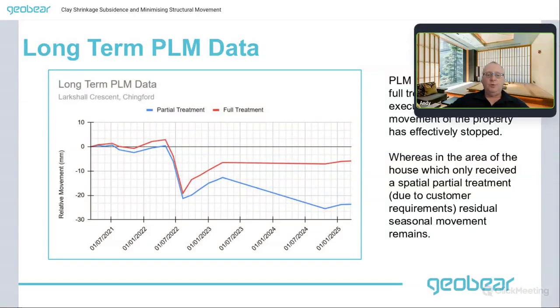Now, you may be wondering what's happening over here, where we have a downward movement and then a rebound, and then a leveling off of movement. And on this part, there is a further downward movement. The data is not complete. There was a data gap, and I've extrapolated between these points. But the reason for the downward movement here is that this part of the structure, from where these measurements were taken, had not been treated. So it shows the difference between full treatment and partial treatment, that the relative amount of movement is different. And that's purely due to the impact of the geopolymer. There's been no other changes, no change in the trees, nothing. The only change was the presence of geopolymer or not.